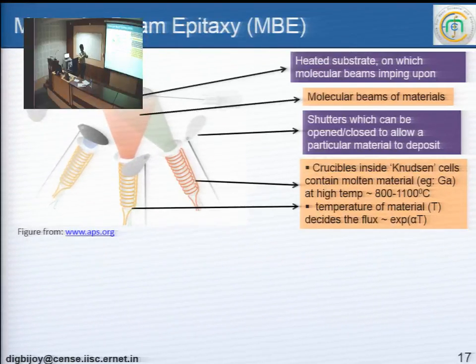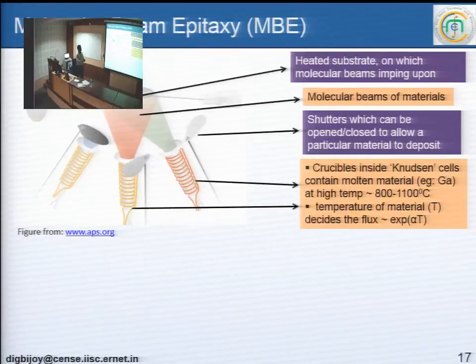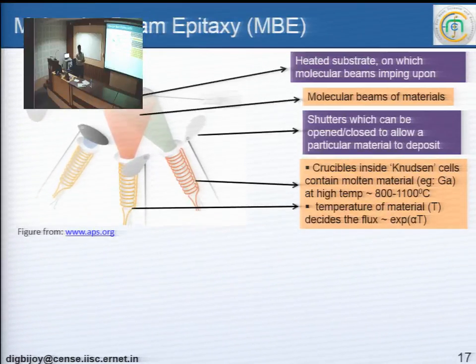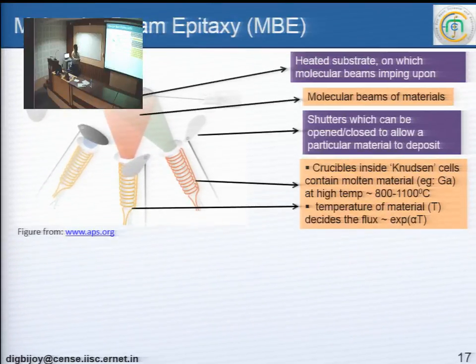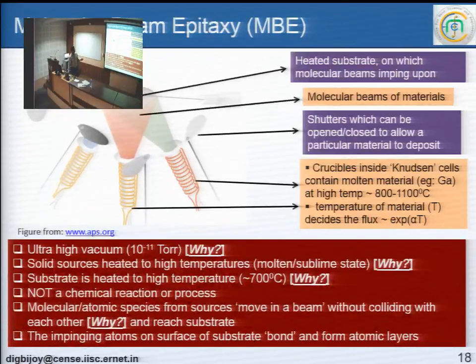Okay. So you can control the thickness of the growing gallium nitride wafer, for example, up to one atomic layer at a time. Okay. So these are called cells, and you have to heat them up really high, of course, like 800 degrees or even 1000 degrees Celsius, etc. Okay, that's how you deposit material. And as I told you, this has to be in very high vacuum, because otherwise the beams will collide and will not even reach here, right? And these have to be heated up to very high temperatures, otherwise they will not give out the beam. This substrate has to be also heated up, because if it's cold, then the atoms which come here will not get energy to move around and bond with each other.